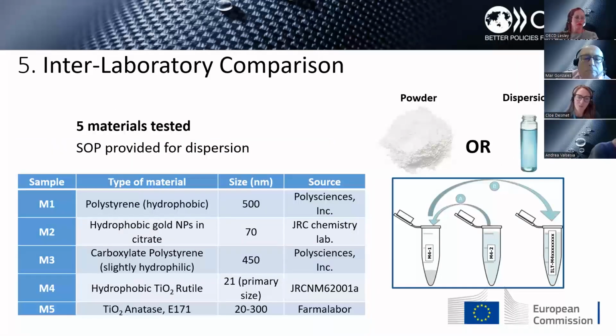The 5 materials tested were provided by JRC either as a powder or as a dispersion. For the powder, we also provided the SOP to obtain the same dispersion for all laboratories. The samples tested were commercial hydrophobic polystyrene, gold nanoparticles stabilized in citrate, more hydrophilic carboxylate polystyrene, titanium dioxide from the JRC Nanomaterials repository, and a commercial food additive which is also titanium dioxide.